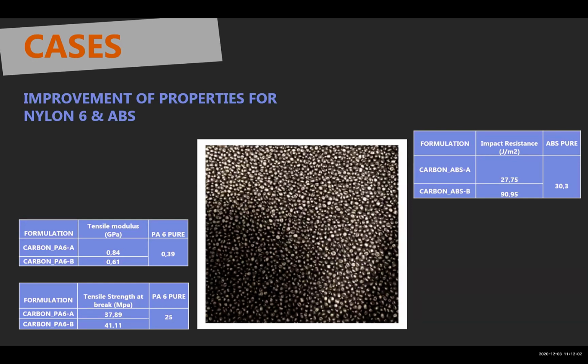When I talk about graphene, it's not just one grade of graphene. We know that there is a difference among graphenes. So we studied this difference, how we can apply nanoplatelets with 10 layers, 7 layers, and what difference we can achieve with that. And so we made what we call G10. It's an internal formulation that we do here to understand how we can apply this nanomaterial inside the polymer matrix, or even for the powder coatings that we are working with in some polymer matrices too, and how we can get the better performance, and how we can sell this to have the balance that I spoke of.